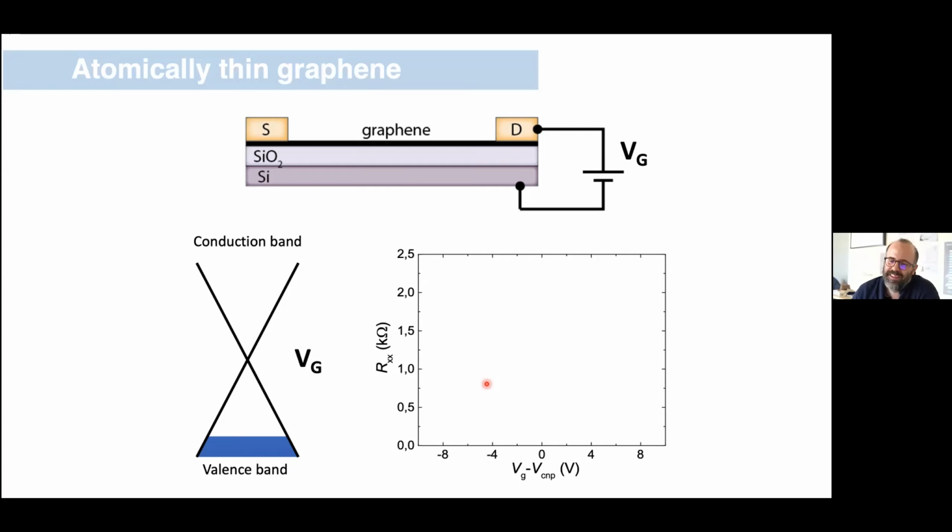So that page is that what I really mean is I apply a potential across my material and I measure how easily the electrons move through the material. I measure the resistance of the material really. And graphene being two-dimensional is interesting in that unlike three-dimensional materials, we can dynamically vary the amount of free electrons that we have in the system. And we do that through gating. So we make graphene one plate of a capacitor, we charge the capacitor, and then the number of electrons that are free to move in graphene becomes controllable.